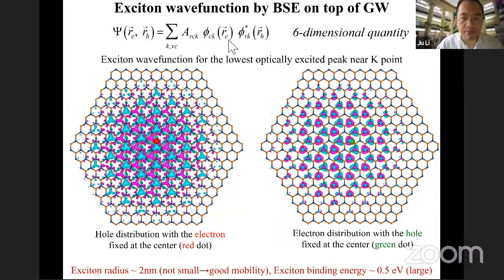And we believe it is type 3 because when we use the Bethe-Salpeter equation to calculate the exciton wave function, you have an electron position and a hole position. So this is a 6-dimensional wave function. And this wave function is about 4 nanometers in diameter. So it's not a small polaron, and that's why we think it's going to have a good mobility. So that's why it's going to move quite far distance. But it's not easy to separate them because it's a 2-dimension material. There is strong Coulombic attraction between them. And so we believe it is going to be type 3.